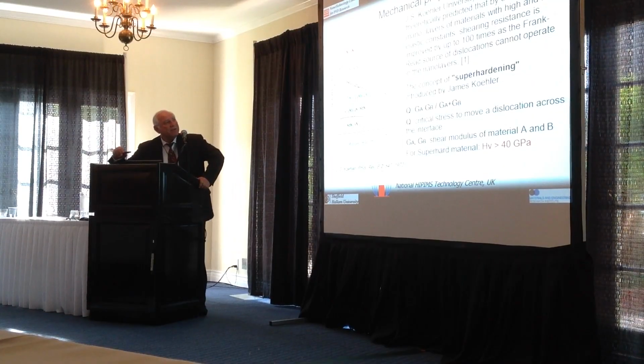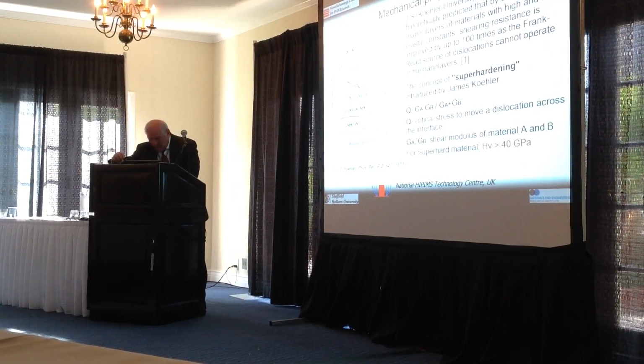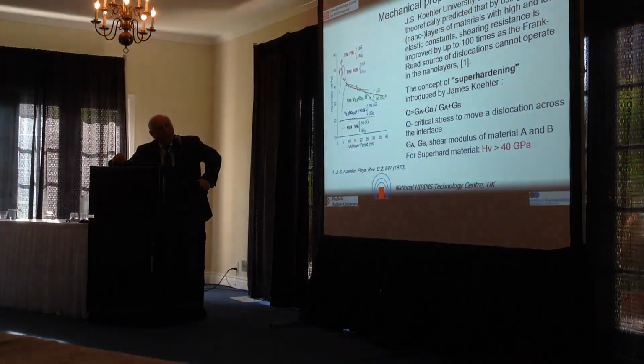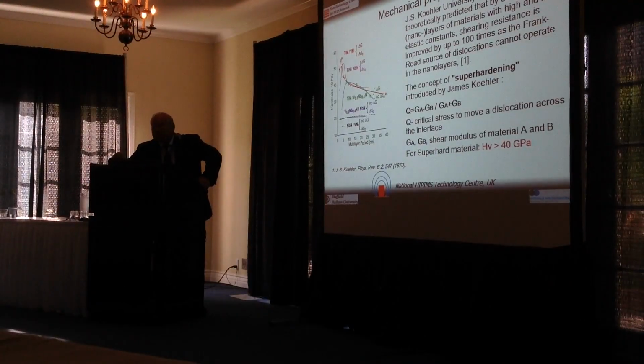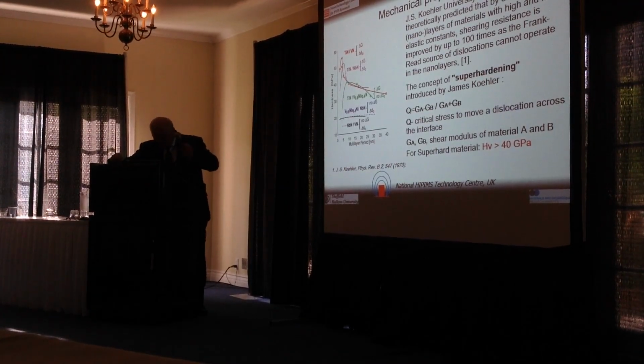And it was demonstrated that a huge hardness enhancement can be achieved in a specific bilayer period range. Now this was the attraction for many years, and the goal was always to get harder materials. Superhardness as a term was introduced, and everything above 40 gigapascal was named superhard.